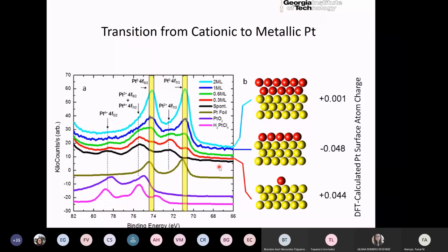early on. Started to start interrupting the interface between the support and the catalyst by introducing a layer of graphene. Now, the layer of graphene could be in between the catalyst and the support itself, having kind of a support of choice below. So this non-identified support material down here can be whatever you want it to be. The ultimate support could be whatever we want it to be, or we could have a support that we choose ahead of time, grow our platinum, and then we use graphene as a capping layer. That means we try to see whether we can do a reaction through graphene. And then we could try to also sandwich platinum in between the two layers of graphene.